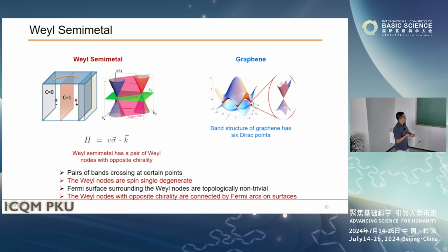But then I think it's 2007 or so, some people in condensed matter rediscovered these things. Actually, because the tools to do condensed matter calculations have been much improved, they can actually predict some materials which are really Weyl semimetals, meaning this compound has some band crossing point in the Brillouin zone, and this band crossing point is split due to spin-orbit coupling and breaking of time reversal symmetry or inversion symmetry. That gives you some Weyl points. And these points, according to topological theory, must be connected by a surface Fermi arc.